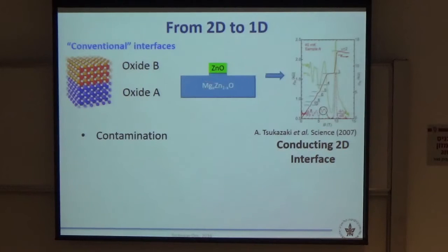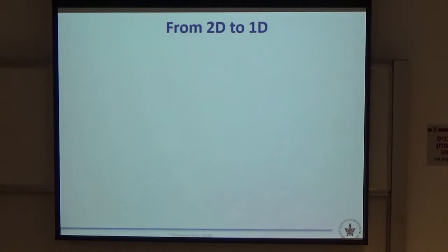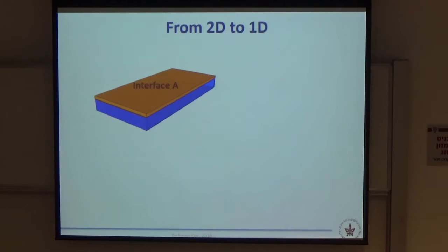The problem with all these processes is that they induce contaminations and also spurious conductivity, because in our case it is strontium titanate, and in strontium titanate, you just remove some oxygen and it becomes conducting, and it's a problem. Okay, so then we came up with another idea. Basically, it's a suggestion of Technion alumnus, now a postdoc at Caltech, David Shibu.